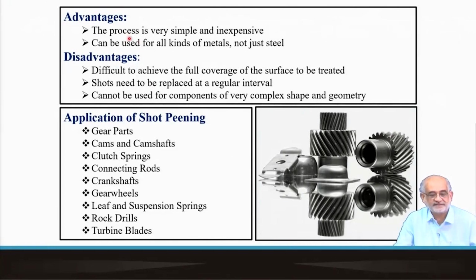So, as I said, there are many advantages. It's fairly simple and inexpensive and can be used for all kinds of metals, not just steel. But obviously, because you're throwing small objects, full surface area coverage is difficult, particularly when you have very sharp corners or difficult geometry. And the shots themselves have to be replaced regularly. Why? Because they themselves get deformed. They are not hard ceramic objects; they are also metals. So they also undergo a certain level of deformation, initially only elastic and then eventually also plastic. And when plastic deformation occurs, the object is no longer 100% spherical, and at the deformed region the impact is no longer a point. The impact can be flattened, or the surface may be flattened. As a result, the impact area is no longer tangential, but slightly broader, and that reduces the stress intensity that you can transfer.